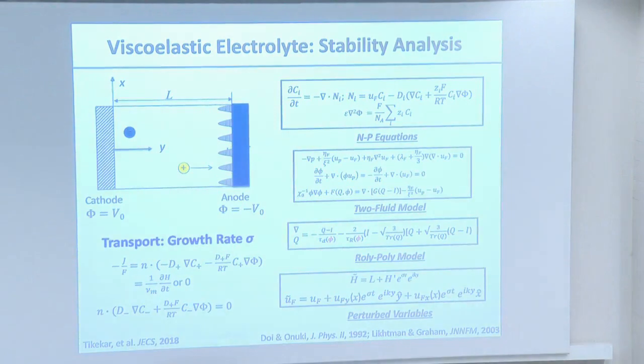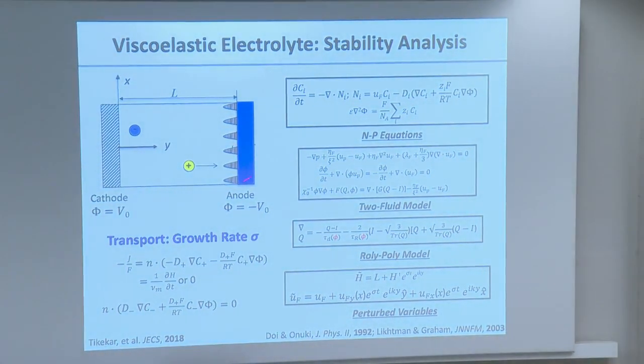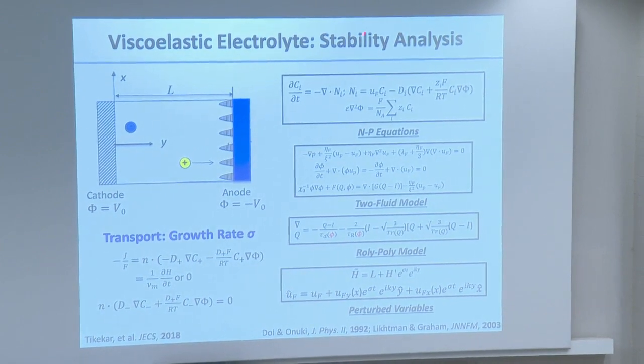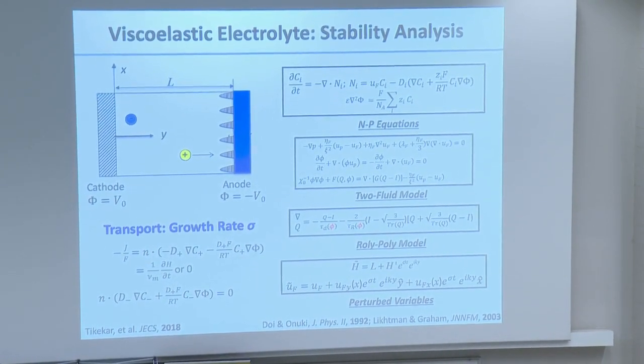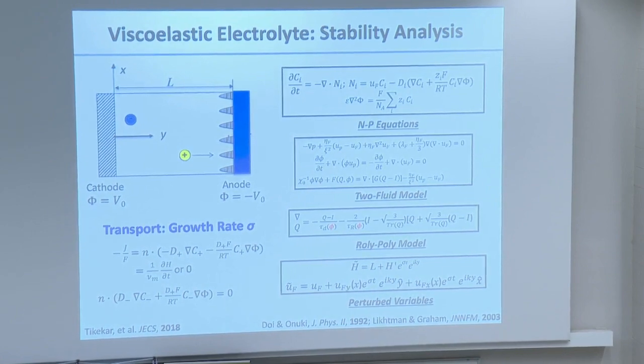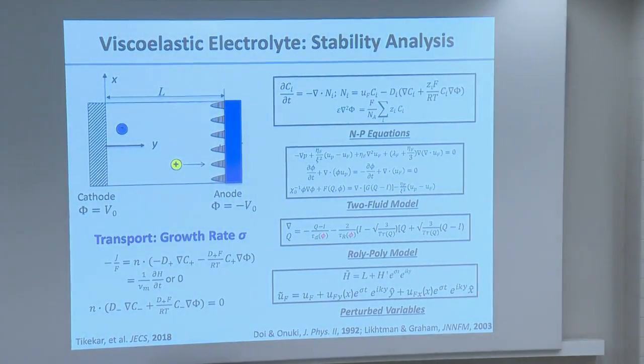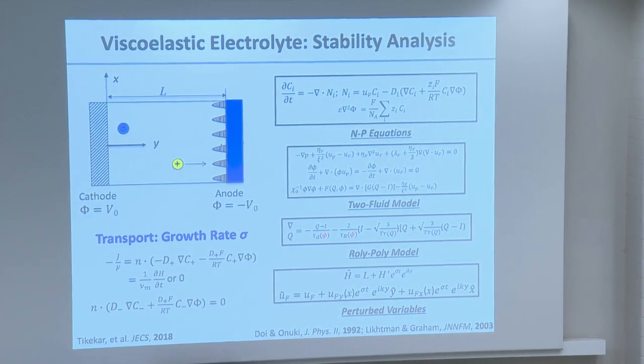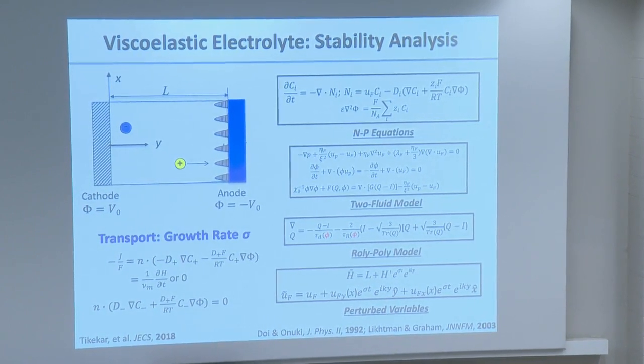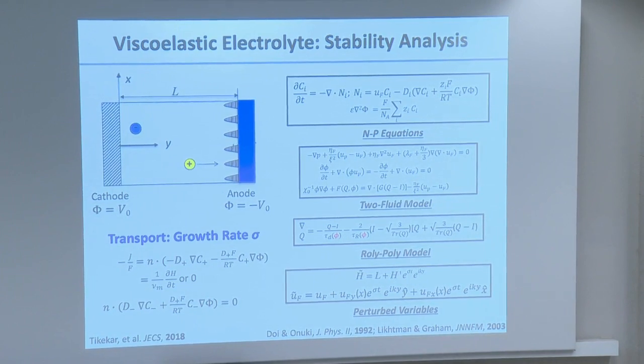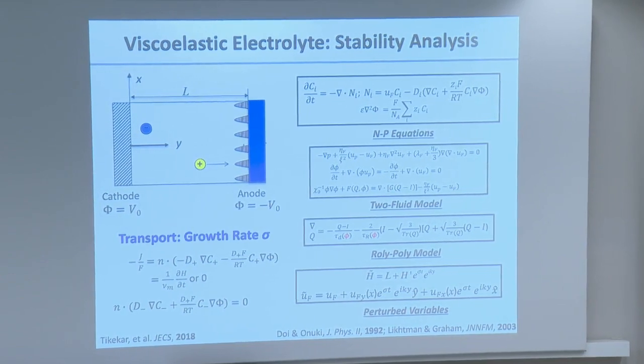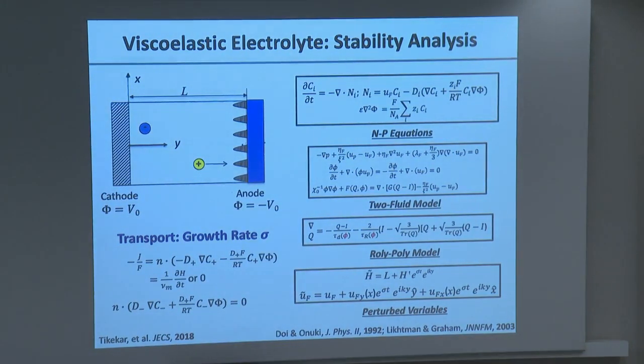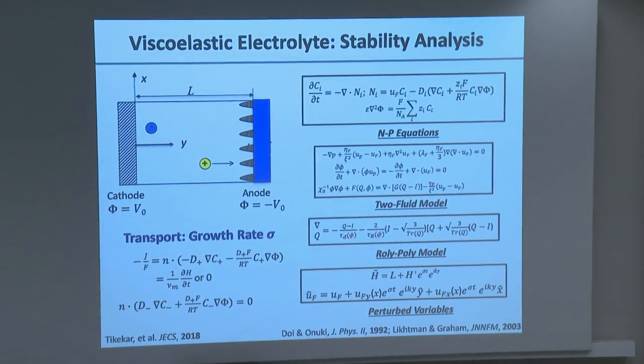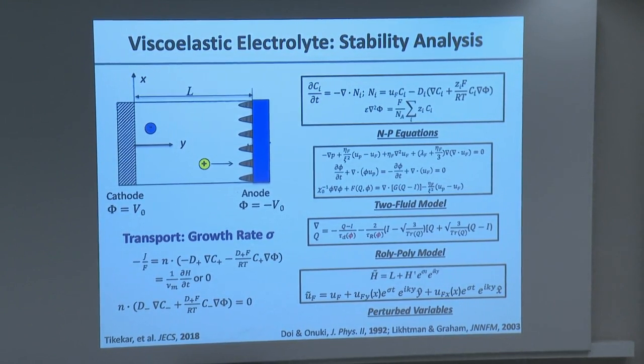So again, more equations, I'm sorry, but I had to do this, all right? So these are the same equations you saw before. These are the same Nernst-Planck equations, except now what we want to do is model them in the presence of a polymer. And when you write down equations for a fluid with a polymer, you need what's called a constitutive law, which essentially tells you how the velocity relates to the stresses. All right, nothing fancy, so don't read every word, okay? And we decided to use this very special constitutive law called the roly-poly model, right? So it sounds cool, right? The roly-poly model is probably the best constitutive model for entangled polymers that is out there. And so we knew that if the roly-poly model couldn't predict what we were observing, nothing could, because this is quite the best model, all right? So that's what we did.